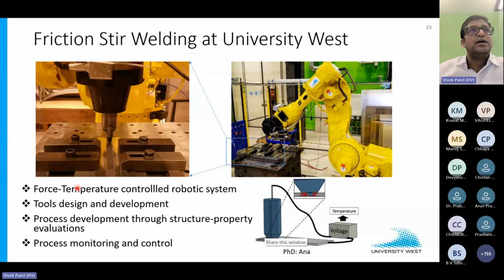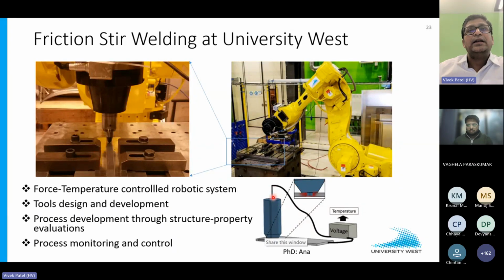So what we have done so far: a few PhD graduates have developed the temperature and force control robotic system. Basically, we have developed a system that can be controlled through temperature. We control this process through temperature measurements, where you can see that we don't insert the thermocouple into the workpiece. Rather, one end of the thermocouple is always fixed on the back of the tool, and the other thermocouple is fixed on one of the contact points of the workpiece.